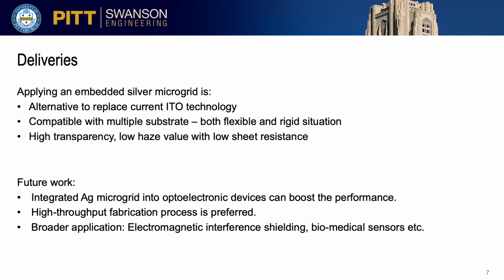In conclusion, applying the embedded silver microgrid is an effective and competitive alternative to replace the current ITO technology. This method is also compatible with multiple substrates, both flexible and rigid. The microgrid samples have a high transparency over 90%, a low haze value, and low sheet resistance as well.